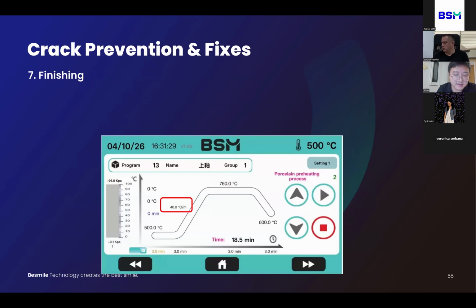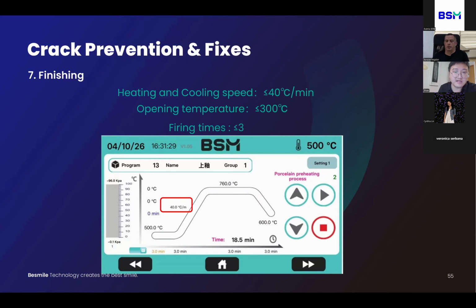Okay. Another thing that we need to pay attention to is the finishing opening temperature and the finishing heating rate and cooling rate. So for the long bridges, the heating rate and cooling rate of the glazing sintering should be no more than 40 degrees per minute. And for the single unit, you can set like 50 degrees per minute or 55 degrees per minute. It is no problem. But for the long bridges, we recommend you set a lower heating rate and cooling rate. And the opening temperature also is 300 degrees.